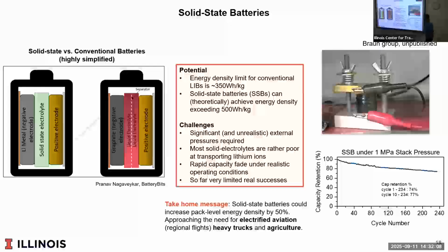At 1 MPa, we have about 20% fade over 250 cycles. That's not good enough for market, but I think it's headed the right direction. We'd like to get to a half a MPa and 1,000 cycles. Then you'd say, okay, now we could make more impact.